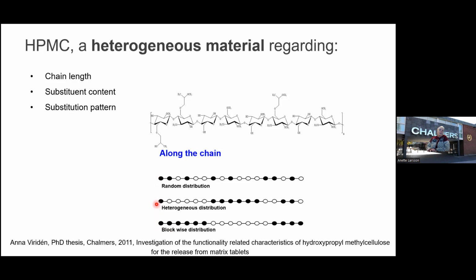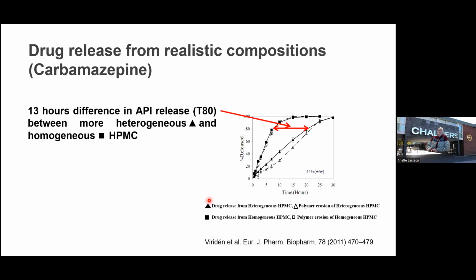So we will compare these two cases here, random and heterogeneous distribution. And here we have the drug release of carbamazepine from the heterogeneous one, and here we have it from one homogeneous one. And you can see that the difference in release rate is 13 hours here. That is a huge problem. If you start to develop a drug formulation using this polymer, and then you get in another batch where you get this, then the whole development is gone. So it is essential to have control over the substitution pattern.